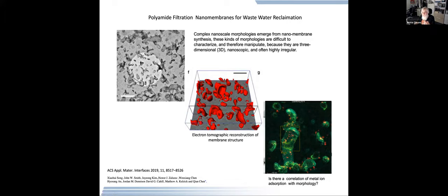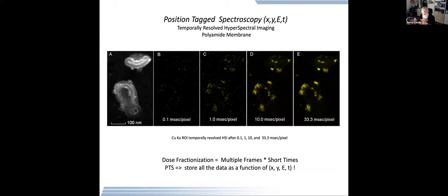Now, of course, the first thing that people are going to ask us is, what about radiation damage, particularly of polyamides? So what we do now is position-tagged spectroscopy. Just like in cryo-EM, we do images as a function of time; here we do spectroscopy as a function of time. Instead of taking one very slow scan, I do hundreds of scans at very low dose, and it acquires a spectrum at every point. Here's an initial image of one of those polyamide membranes. Here's a spectrum taken at a tenth of a millisecond per pixel, not much data. But we can do repeated frames and go from a tenth of a millisecond to 1 millisecond to 10 to 33 milliseconds, and now we can see the correlation.